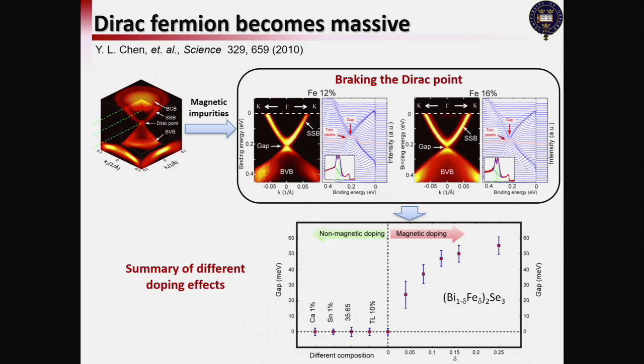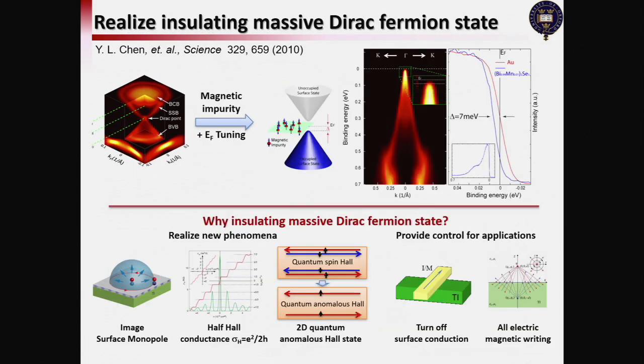Well, and then of course, if we break the time reversal symmetry, the surface state becomes vulnerable, and the degeneracy of the Dirac point no longer holds, and that's what we observed. We put a lot of iron into the system and saw that the Dirac point now shows a dent. This is indicating the opening of a small gap. And then if we tune the chem potential into this tiny gap, we realize this massive insulating massive Dirac fermion state that can be used to realize all these exotic phenomena proposed by Shoucheng and theorists in the field.